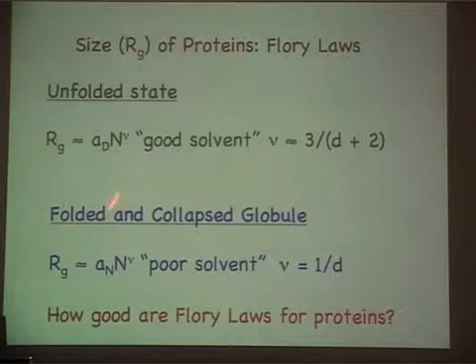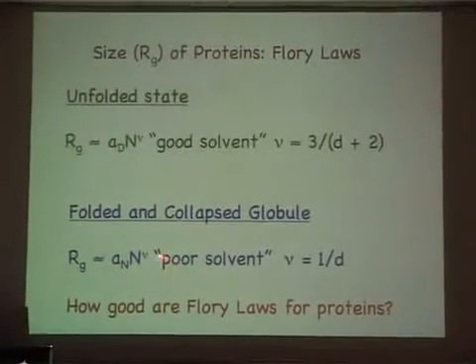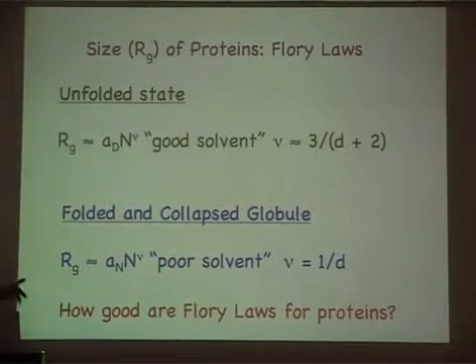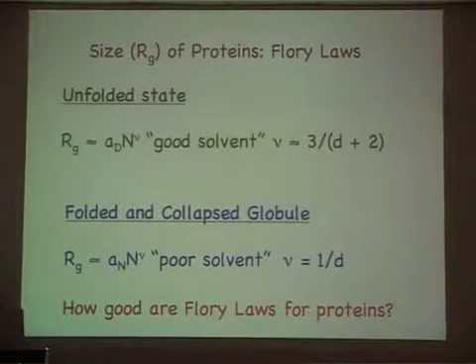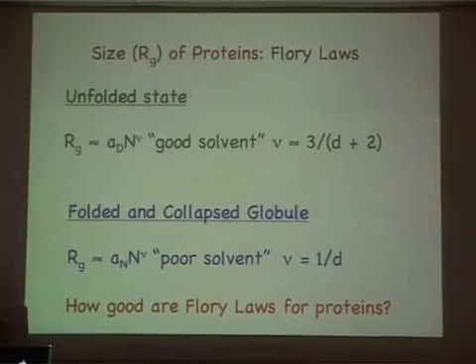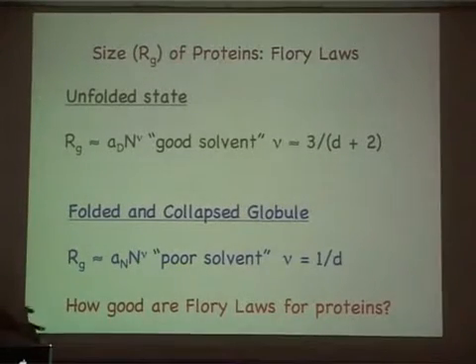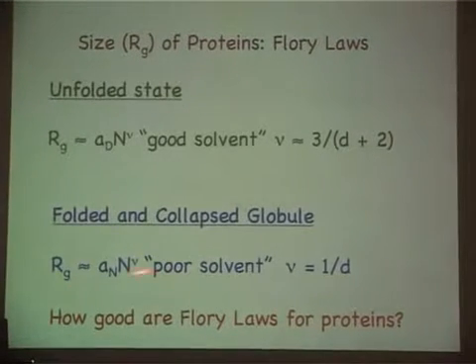If the folded state and the collapsed globule are maximally compact, then you expect the radius of gyration should scale as N to the nu times its prefactor, and this means that the solvent is poor. Usually, for most proteins, neutral pH water at room temperature is a poor solvent, and Rg will scale like this, and nu will be 1 over 3 in 3 dimensions.